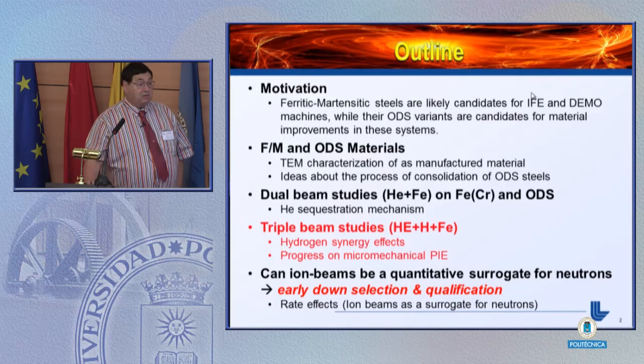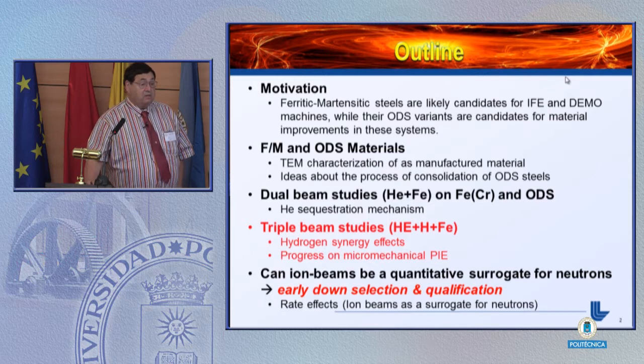Probably the most important thing I want to talk about, and therefore I'm going to give somewhat short shrift to the items on the top of the list, is the whole question about can ion beams be a quantitative surrogate for neutrons? And can we use them in such a way that we actually can make early down selection and qualification of materials, reducing the risk and uncertainty, the risk primarily being an economic one, in the selection of materials? And can we, in fact, sort of pull ourselves up by our bootstraps, and by doing this type of analysis, actually bring ourselves to the point of having a demo inertial fusion energy machine that then can serve also as a materials test bed for developing more advanced materials for inertial fusion energy. At the heart of this, the physics of all of this, is the so-called rate effects, and that's what I'm going to speak about at the end of this talk.